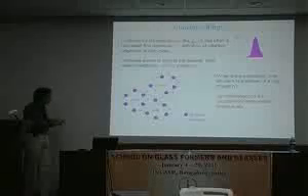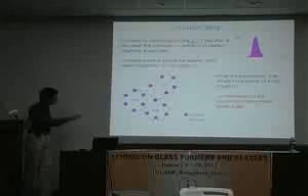So a loop is: you start at one silicon atom, and you take one of the bonds to oxygen, which is attached to a silicon, and you take another random oxygen, and so on until you come back. The shortest loop that brings you back to the same silicon atom is called the size of the corresponding ring.